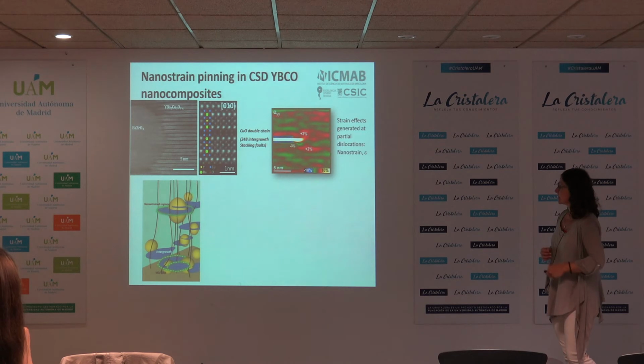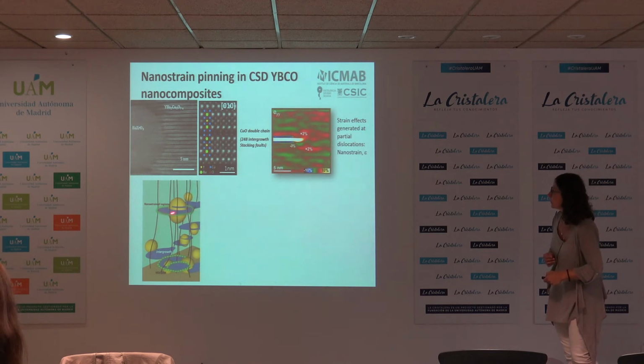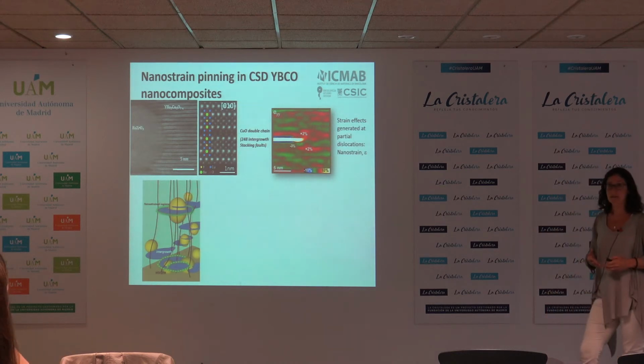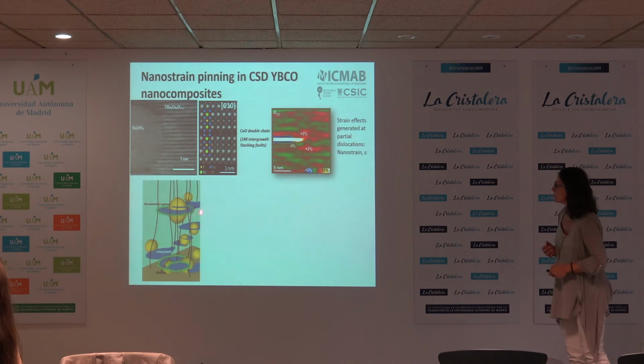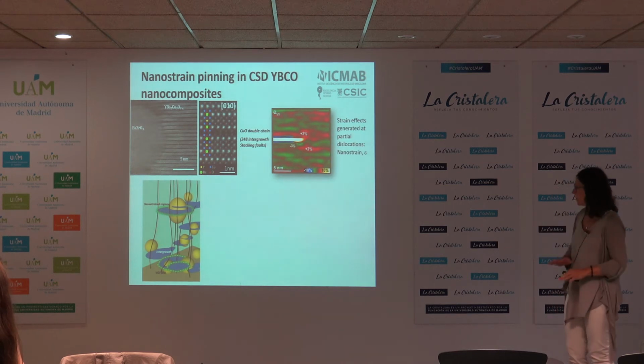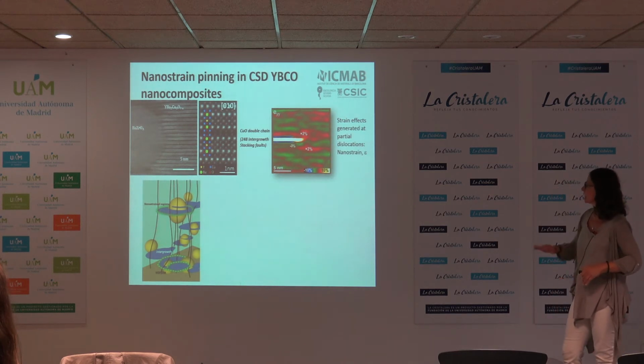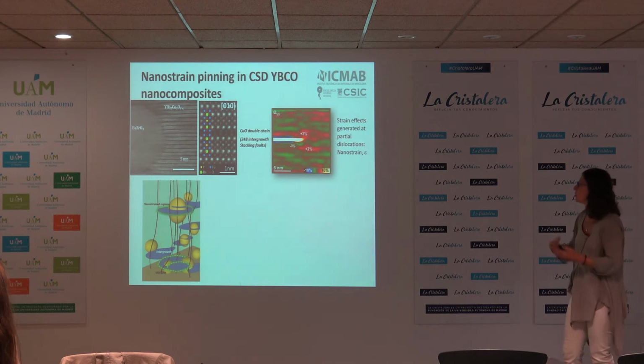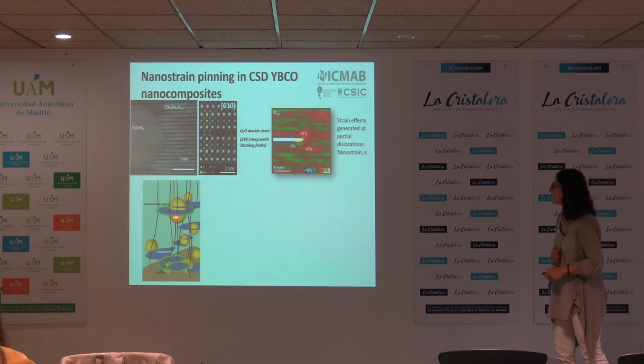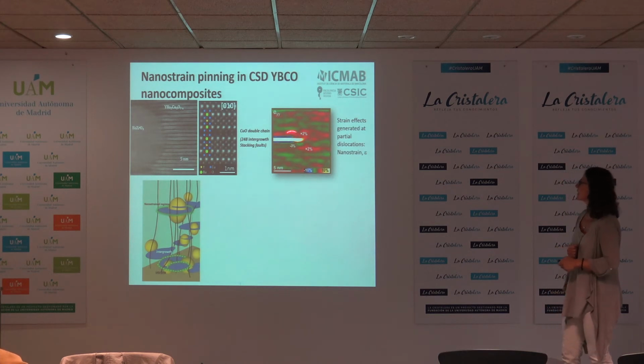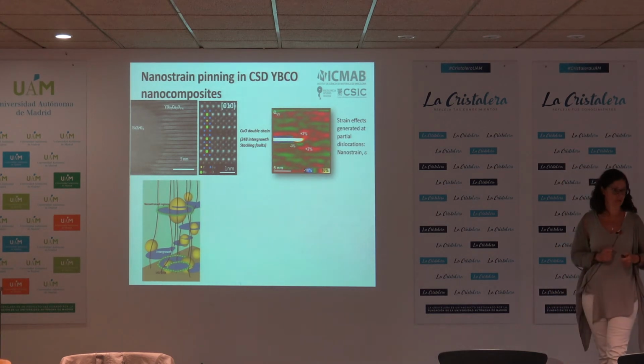This layer is like you see here, this blue thing, okay? So these are intergrowths. These yellow balls would emulate the nanoparticles. These intergrowths are these blue areas, which are called stacking faults, or 248 intergrowth. And at the end, at the surrounding of this intergrowth with the YBCO matrix, which would be all this, we see that there's a lot of strain which is also accumulated.